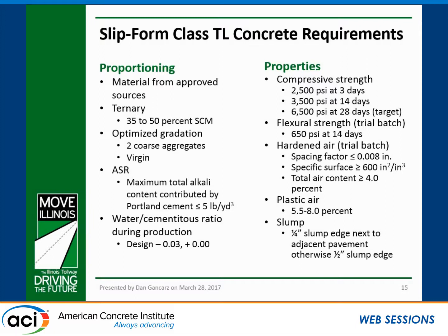So we also evaluate flexural strength during the trial batch only, just to verify we're getting 650 at 14 days. We evaluate hardened air during the trial batch, evaluate spacing factor, specific surface, total air content greater than 4%. Plastic air is required to be between 5.5 and 8%. And then slump is the contractor's option. So they can place it whatever slump they need to get adequate consolidation. The only thing we evaluate is the slump edge after placement. So we're looking for a maximum of a 1/4 inch slump edge between adjacent lanes, and then if it's a free edge, we're fine with a 1/2 inch.